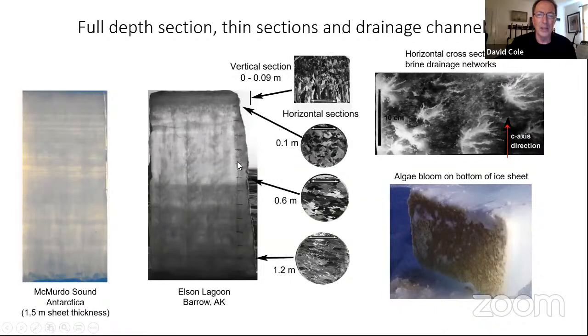Kind of hard to see scales. These are 10 centimeter increments. So this is about a 1.4 meter thick slab. This is about a 1.5 meter thick slab from Antarctica. You see horizontal banding. The banding features are due to variations in brine porosity and mostly growth rate variations up top, but then once the sheet gets kind of thick, they're going to be coupled with changes in current and such under the ice that also help govern how brine inclusions develop and form these layers.